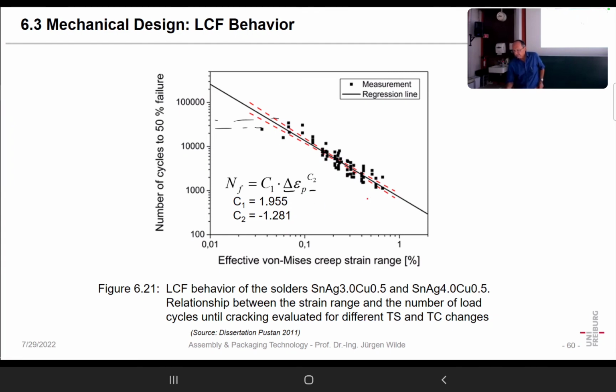And you see there's a large scatter, but here we have a certain law that defines when, for instance, we have 1% of strain range, we have only, what is it, 600 or so cycles until the specimen fails. When we have 0.1% of strain range, that means 1 promille of strain, then it will live for 10,000.